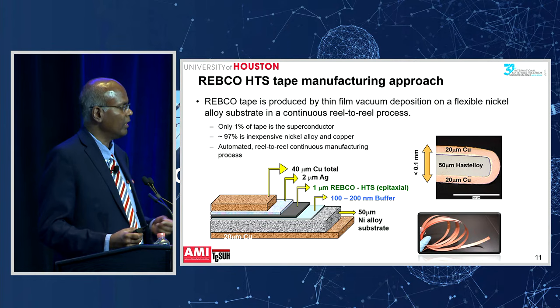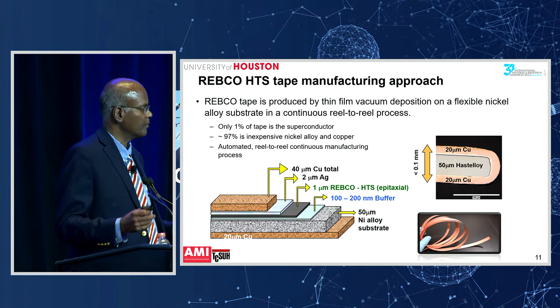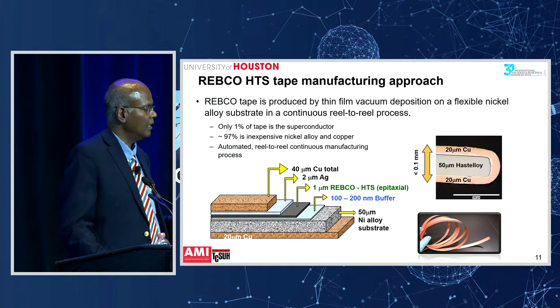And the Hastelloy provides the substrate over which you're growing several films. And then you have a buffer layer. I'll talk about the buffer layer in a couple of minutes. And then you have a superconducting film. You can see the superconducting film is very thin.